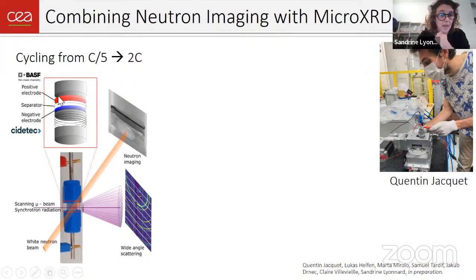What Quentin is doing basically is assembling batteries using the materials from the project prepared by the industrial partners, BASF regarding LNO and Cidetec regarding graphite, and putting these materials in the Swagelok type battery. And this battery is exposed first to the white neutron beam from the ILL, and neutron imaging is performed operando. And then the very same cell, cycled in the same conditions, is brought to ESRF, and a micro XRD experiment is performed. Cycling is a typical standard cycling procedure established in the project, going up to 2C. So it means this is a C rate, so the speed at which you cycle the battery. So this is quite fast.